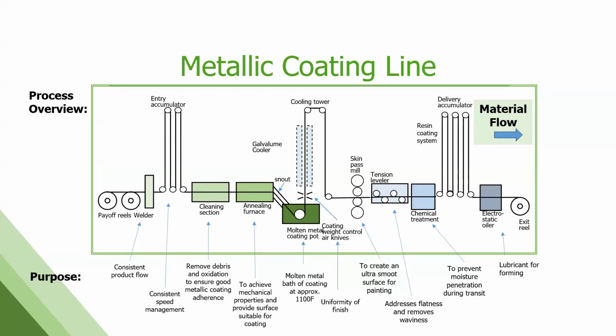So we load 2 coils at the entry on the left, and it goes through an accumulator tower. These towers allow us to take up slack and let slack down in the steel so that we can continue running while we stop one end of the line and weld the next coil to it, so we don't ever stop. And these lines can run continuously for 30 to 60 days without having to come down for maintenance, 24/7. That's what they're built to do.